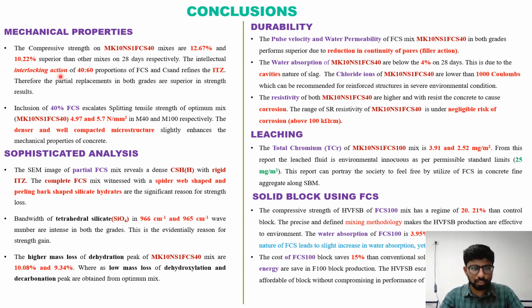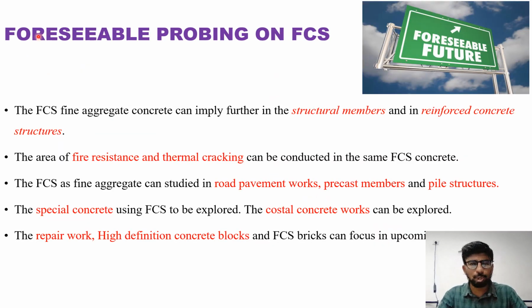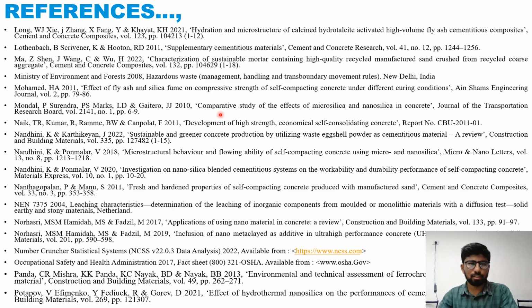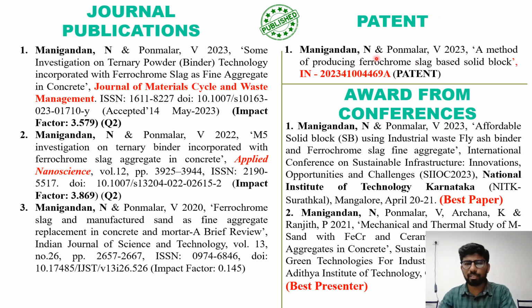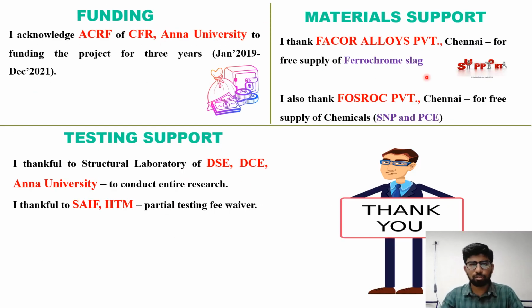This is due to the interlocking action of the 60-40 proportion of M-sand, ferrochrome slag and C-sand, which rigidifies the ITZ. The well compacted microstructure and spiderweb shape are the reason for the strength gains in the complete replacement. Durability at 40% also performs better. Leaching also performs well, and with a precise mixing methodology we get affordable solid blocks. These are the various possible future research areas. These are some of the journal publications, and a patent for a method of producing solid blocks has been published. This is the award from NIT and other institutions for our papers, and this is the funding I have to thank in acknowledgement.